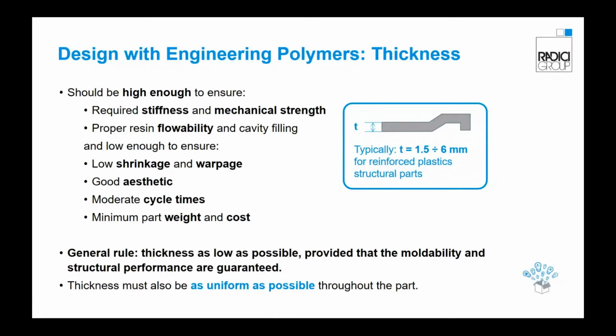Another important aspect is to design the part with thicknesses as uniform as possible throughout the part, in order to avoid differential shrinkage during the molding process. Typically, the thickness of plastic parts for structural applications ranges from 1.5 to 6 millimeters.